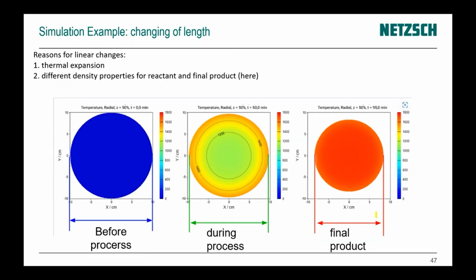The next part, which is also very important, especially for the curing, is the change of the linear size of the polymer. It is known that the polymer will change its linear size, its length, during the curing. And here it is very important, for example, for some processes like lamination, because delamination can happen. And in our software, we can simulate the change of the length. We can see what the length is before the process, before curing, during the process, and what the final length is.